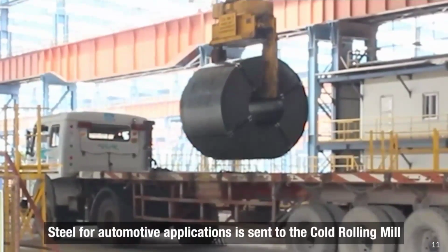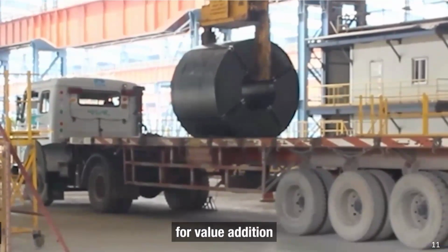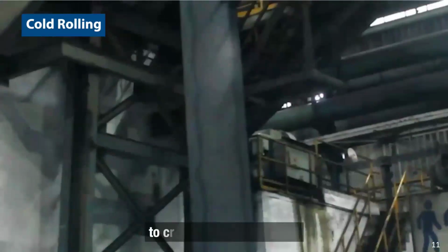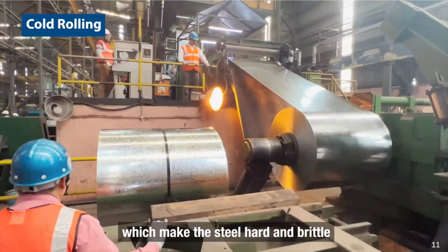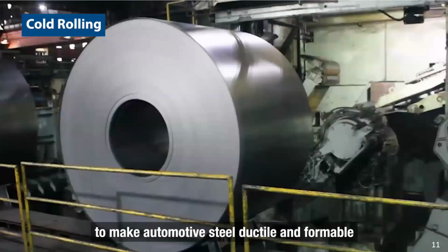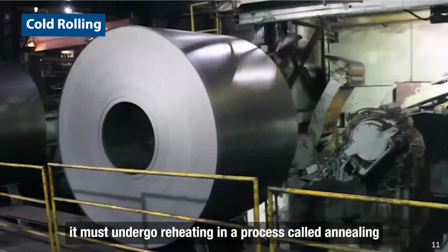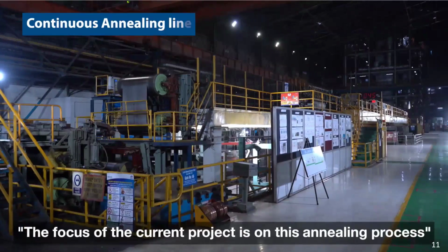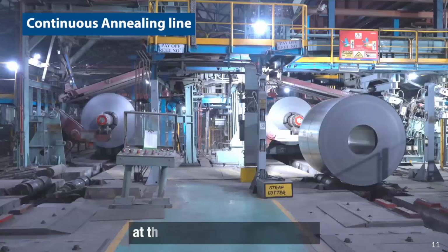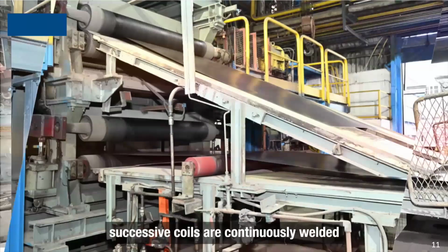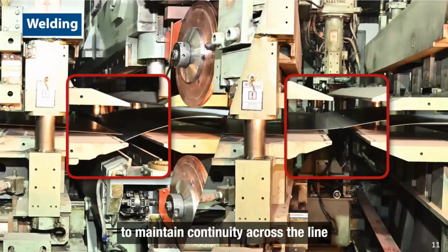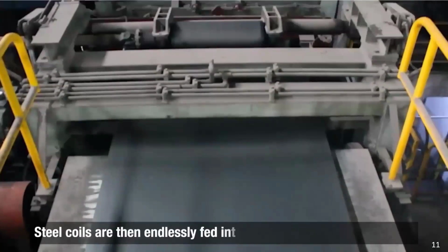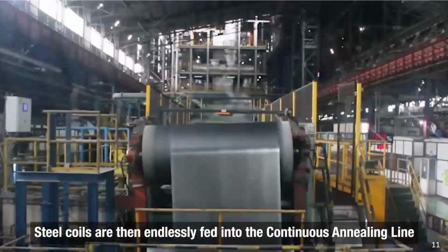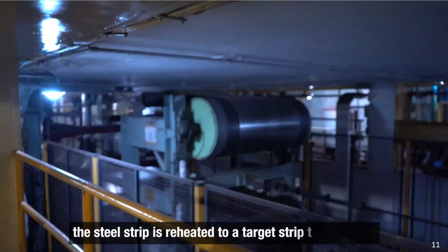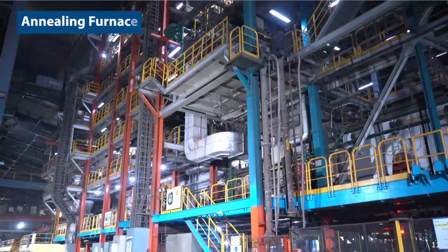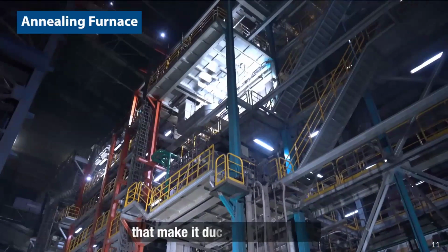Steel for automotive applications is sent to the cold rolling mill for value addition. Here, hot rolled coils are pickled and rolled to create cold rolled sheets, which make the steel hard and brittle. To make automotive steel ductile and formable, it must undergo reheating in a process called annealing. The focus of the current project is on this annealing process. At the continuous annealing line, successive coils are continuously welded to maintain continuity across the line. Steel coils are then endlessly fed into the continuous annealing line. In the annealing furnace, the steel strip is reheated to a target strip temperature to allow the strip to regain mechanical properties that make it ductile and formable.